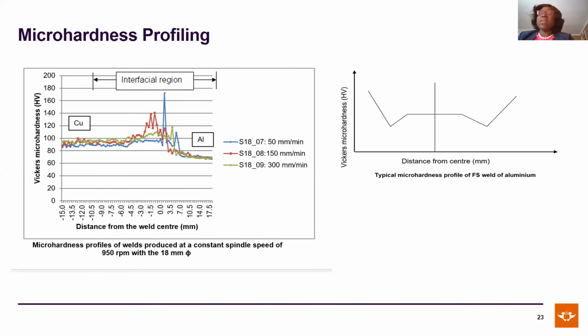Further to this, another basic characterization which we will always conduct is microhardness profiling. The picture on the right-hand side gives typical Vickers microhardness profiling of friction stir welds of aluminum. So when aluminum and its alloys are welded, the stirring of the tool during the welding process usually leads to a softening, and this softening then leads to the hardness of the stir zone being stable, looking at the plateau that is observed in the right-hand side corner.